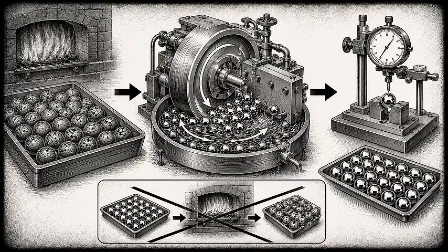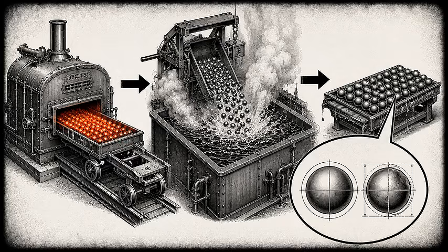The result is a ball hard enough to survive those punishing point contacts without permanently deforming, and tough enough not to shatter under shock. But hardening warps things. The volume change as the steel transforms, combined with the fierce thermal gradients of the quench, means that every ball comes out of heat treatment slightly distorted and slightly the wrong size. The sphericity so carefully generated before hardening has been partially spoiled by the hardening itself, which is exactly why the work is not finished before heat treatment.